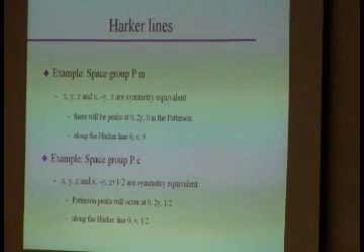Okay? That means in Patterson space we use UVW as our interatomic distance coordinates, remember? That means we'll have a Harker line 0v0. We'll have a lot of peaks there, because every single atom in that unit cell will generate a peak somewhere on this line depending on its y coordinate. Okay?